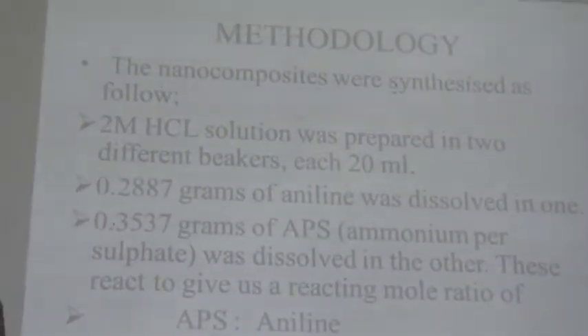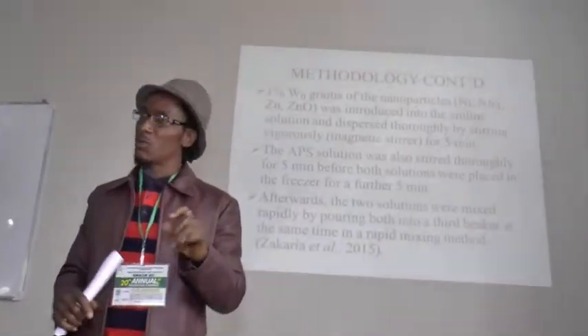Next slide, please. Now first, we have to synthesize the polymer. Polyaniline was synthesized from the aniline monomer using the oxidative polymerization method, where we dissolve the aniline in acidic medium, dissolve the oxidant, that's APS, in acidic medium, and pour them together rapidly at the same time in a third beaker. This is known as the rapid mixing method by Zakaria et al.. First, the amount of monomer used was 0.2887 grams of aniline, against 0.3537 grams of APS.